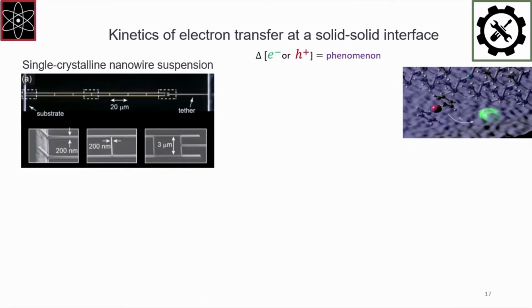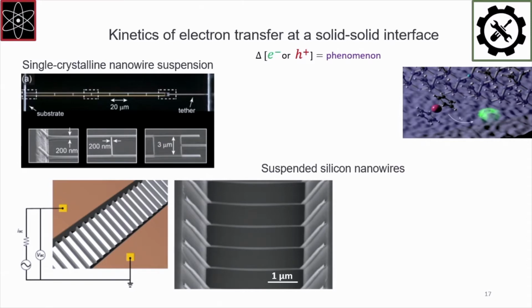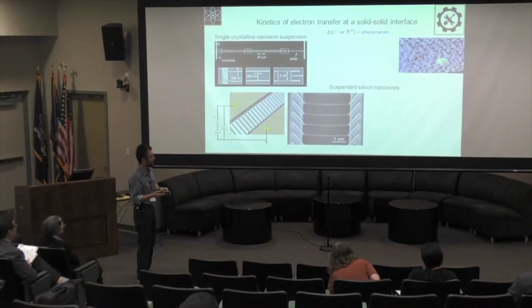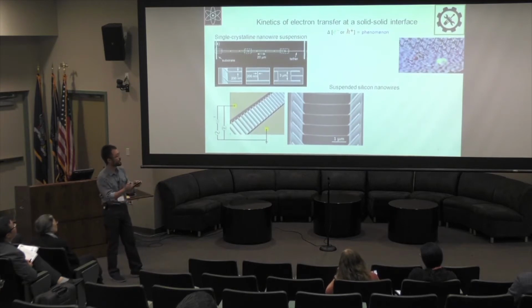So I mentioned that we learned how to make these suspended single crystal structures of nanowires. And why not just make an array of them and use them as the actual sensor for this charge transfer doping process? So we suspend them. In analogy to FinFET, where you want to maximize your area that's in contact with the gate, I think it would be nice to fully release them from the substrate so that the process can happen all around it.